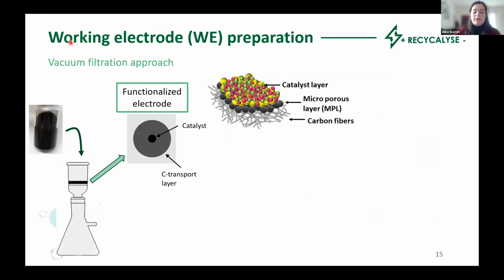So now we need to prepare the working electrode, and this is done via a vacuum filtration approach. During this approach, the catalyst is deposited on a transport layer. And this transport layer needs to be porous to allow the reactant stream to reach the catalyst. We started by using a carbon-based transport layer as it is commonly used in fuel cells. And after deposition of the catalyst, we obtain such an electrode, and here you can see a cartoon of it.